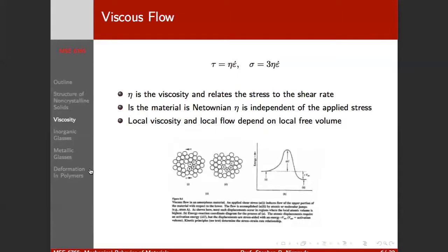There was a heading that was sort of lost here, so take a second and just write in shear transformation zone, right? So the idea in an amorphous material is the local unit of plasticity, the carrier of plasticity, is essentially a local rearrangement of a small atomic cluster locally under the influence of a shear.